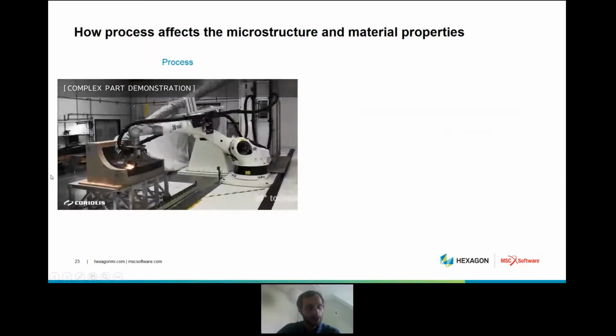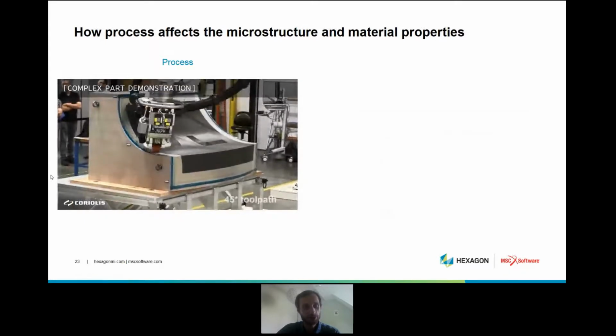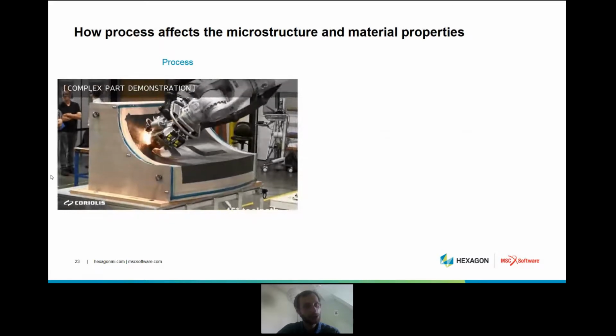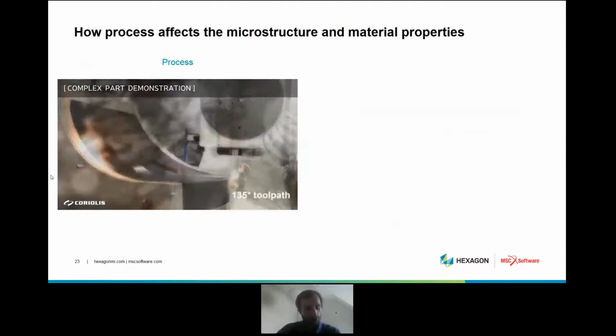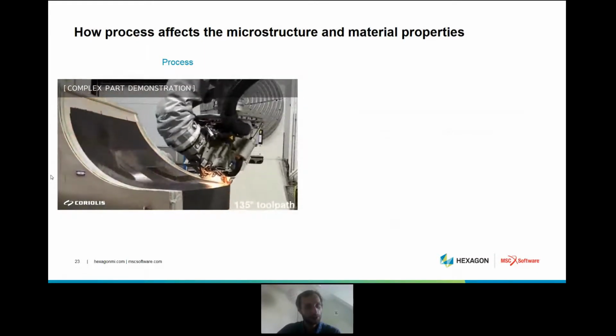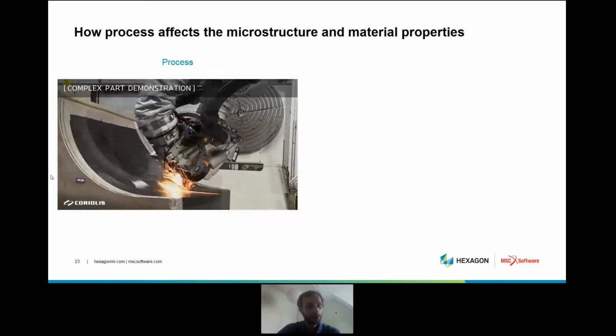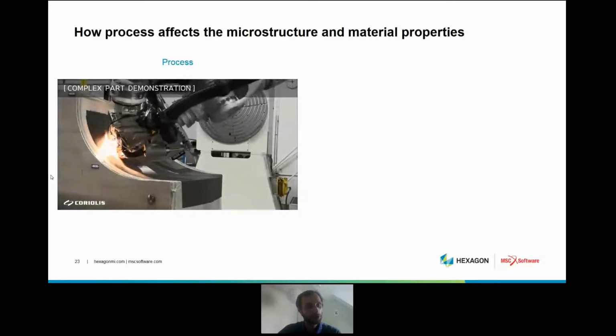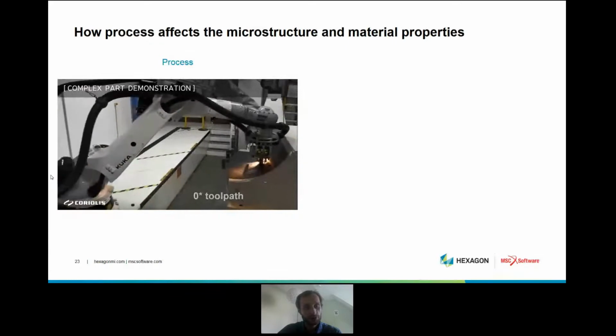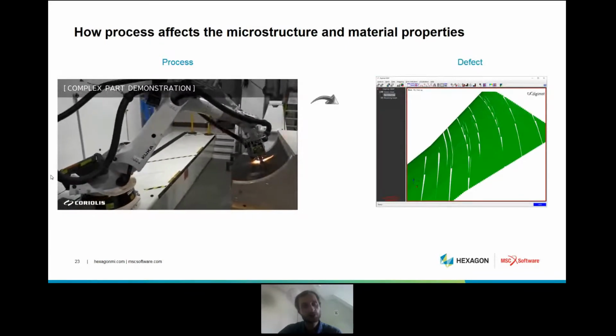So how does automatic fiber placement work? Well, this is, as you can see, an automated manufacturing technique, which goes hand in hand with the digitalization topic, obviously. And so what we have is tows of material, which are usually fibers that are pre-impregnated and are deposited following a discretization of the part geometry that we want to reach. As part of this discretization, we cannot perfectly cover the desired geometry. To do this, we would have to have very, very narrow material strips, and it would not be possible from a physical perspective. So as engineers, we need to live with the defects that are introduced by the process.